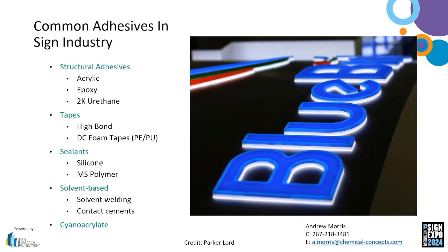So the substrates have to be totally clean, they have to be really well abraded, it's going to take you a lot of prep steps. And the acrylic adhesives, or MMAs, have really overtaken in that if you were to do a line chart of adhesive uses by chemistry over time, you see this really big growth pattern for MMAs, and they've been adopted because they are almost surface prep free. So you just do a solvent wipe, make sure your parts are clean, glue them together. If there's a little bit of surface oils on the thing, the methacrylic acid in the product will cut into that, for some products more so than others. So prep is still an important step, but it's more minimal.